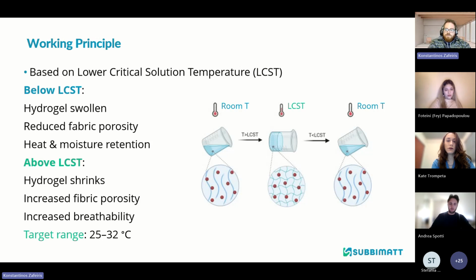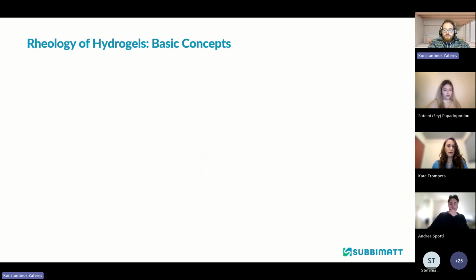Now, the hydrogel function is based on the lower critical solution temperature, as we referred to before. Below this temperature, the hydrogel is swollen and, when in a fabric, reduces porosity and retains heat. However, above the lower critical solution temperature, the hydrogel shrinks, porosity increases, and so does breathability. For textile applications such as SUBBIMATT, the critical requirement is that this transition occurs within a range of 25 to 32 degrees Celsius.